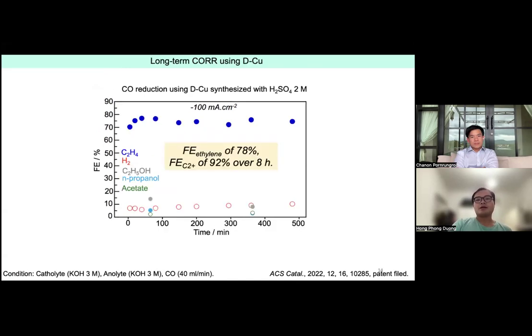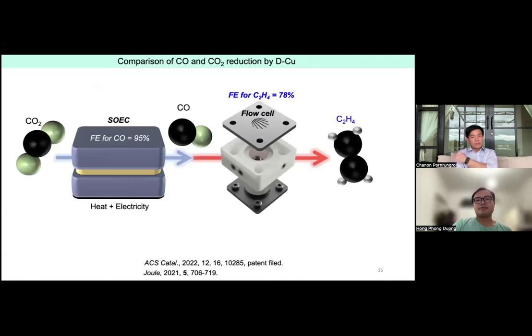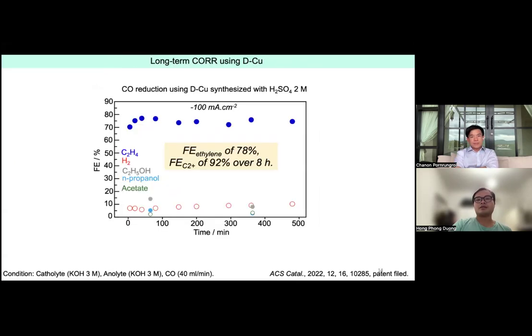And then we performed the long-term electrolysis to know if the system is stable or not. And it showed that it is quite okay. Over 8 hours, we can get almost 80% Faradaic efficiency for ethylene, and even for C2+ products, we get more than 90% Faradaic efficiency.